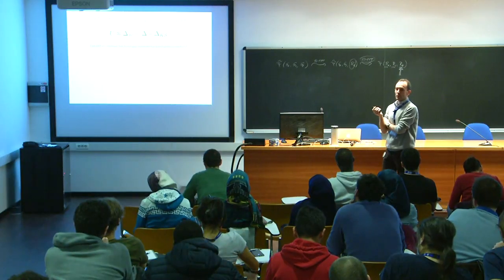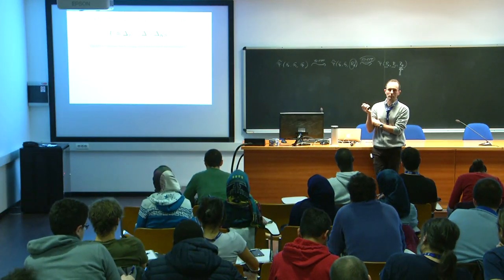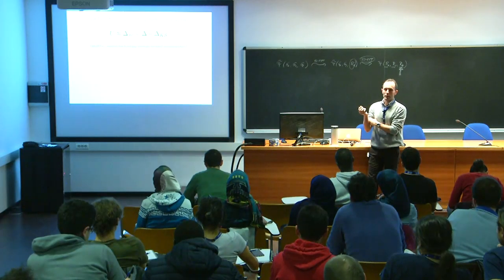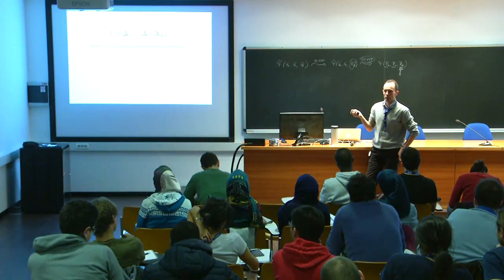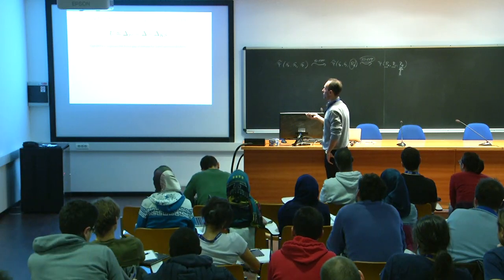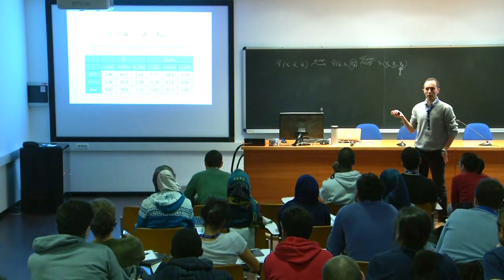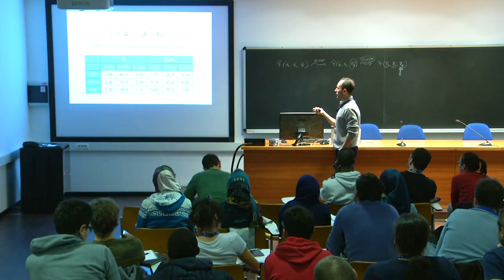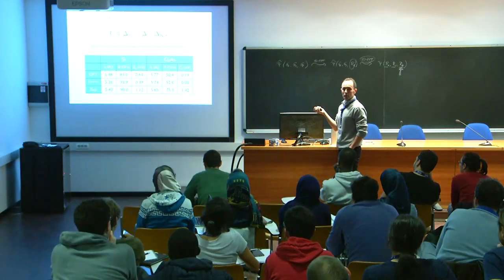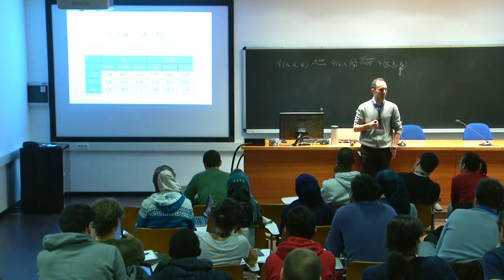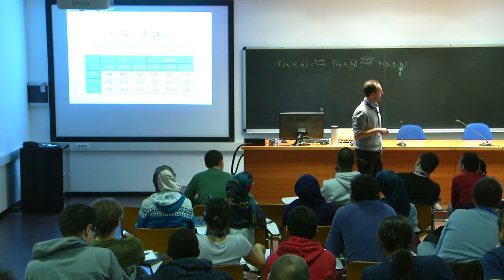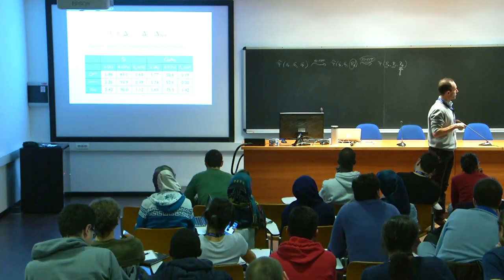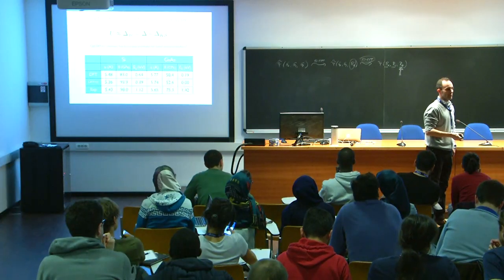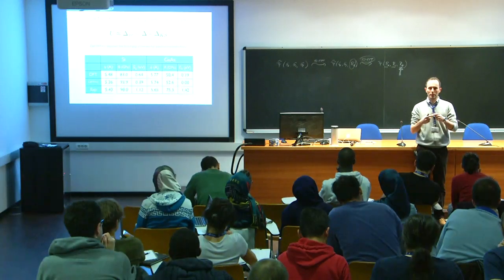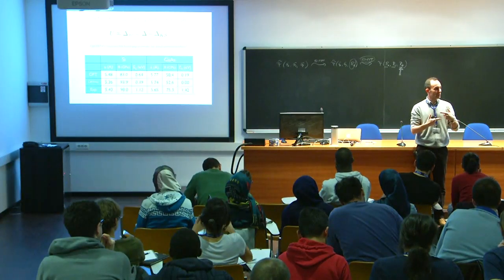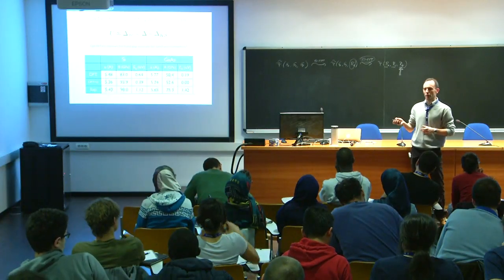On the other hand, we have learned that this U might also be understood as a simple way to reintroduce the discontinuity of the exchange correlation functional or potential into the Koopmans system. So what happens if we use this with silicon and gallium arsenide? You see that the band gap actually gets corrected, but in the wrong direction, so it gets decreased. So this is opposite to what we obtained so far with other types of material. And that's exactly due to the thing that I was mentioning, that the +U improves localization by suppressing hybridization, right? And in these materials, actually the band gap is a bonding, anti-bonding one. So it's based on hybridization. So suppressing hybridization means suppressing the band gap. And so you get in the wrong direction.